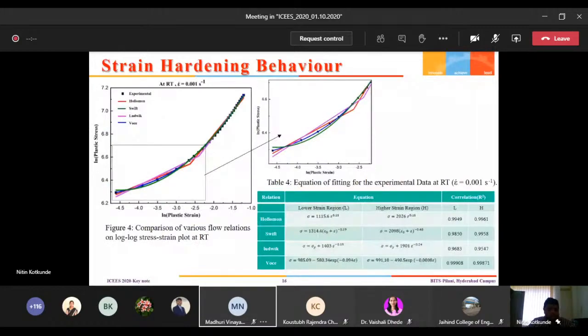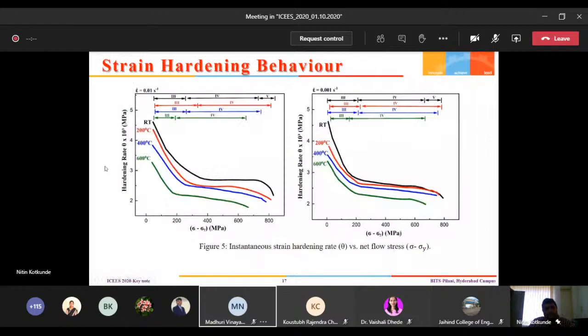So the deformation behavior is slightly more complicated, and we have seen that the Voce equation is perfectly suited to predict the deformation behavior of the material. These are the different stages. We have plotted the instantaneous strain hardening rate versus net flow stress, and we realize that the deformation in the material usually happens at the third stage, fourth stage, and fifth stage. Usually for any material there are five stages of deformation. So this material follows the third, fourth, and fifth stages of deformation.